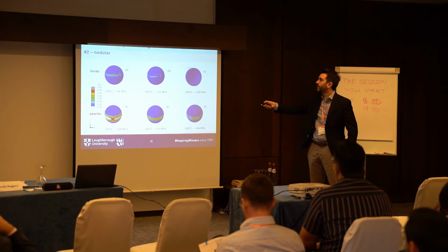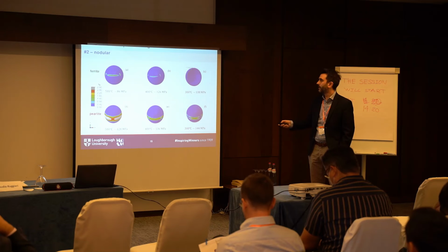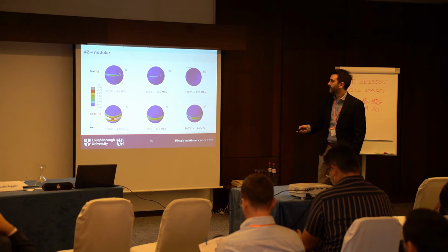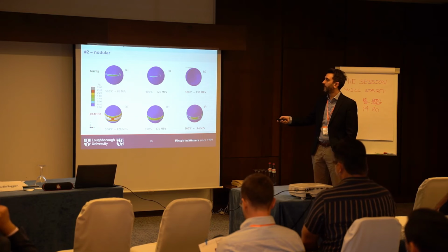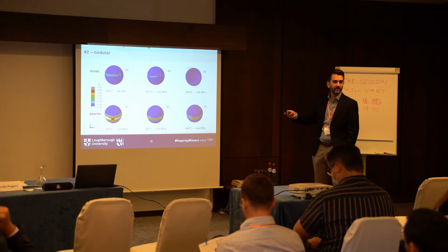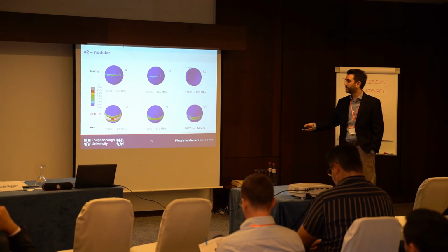A few nice images again from the second model now, and the second again is heating up, then applying the side load. Nodular shape in two different cases, ferritic ring or pearlitic ring here. The main point here is just this label that when you have a ferritic ring around it, you have damage at around 80 or 90 megapascals. It's much later when there's a pearlitic gradient, and that propagates throughout the different temperatures.